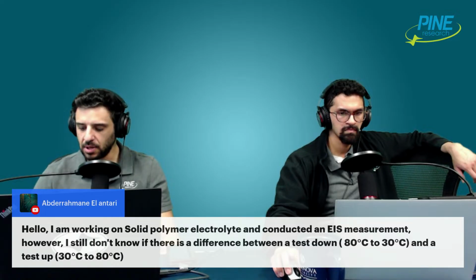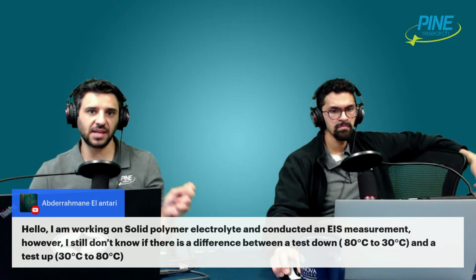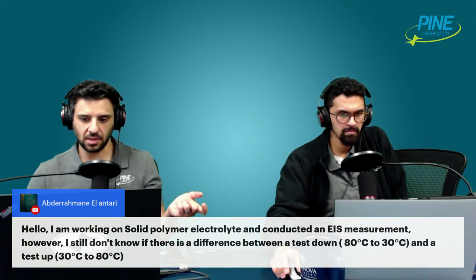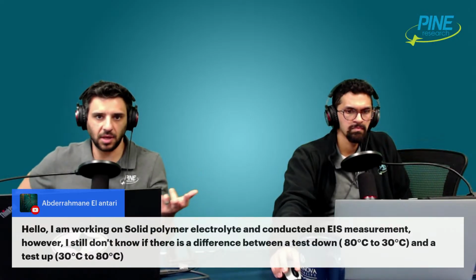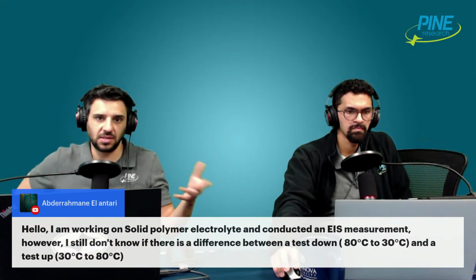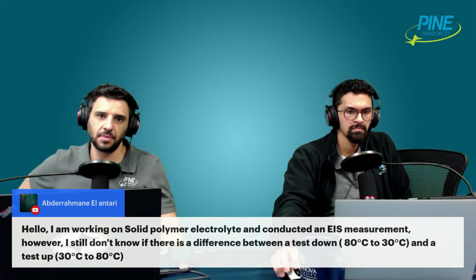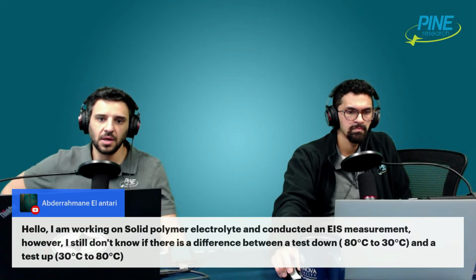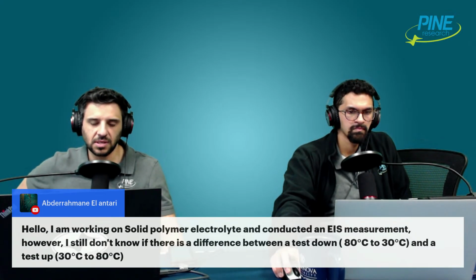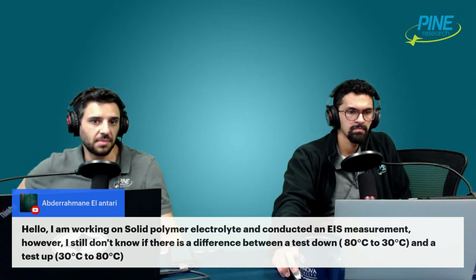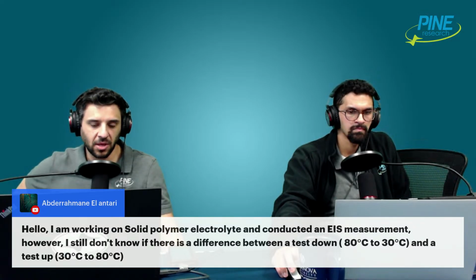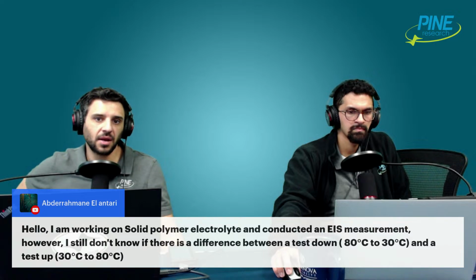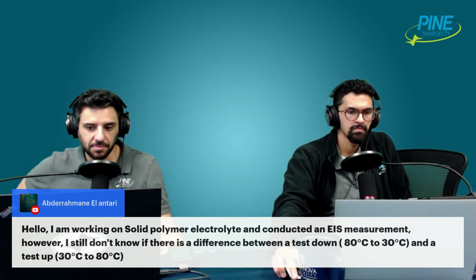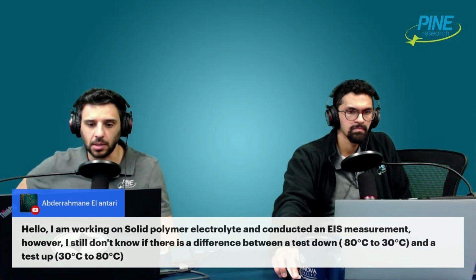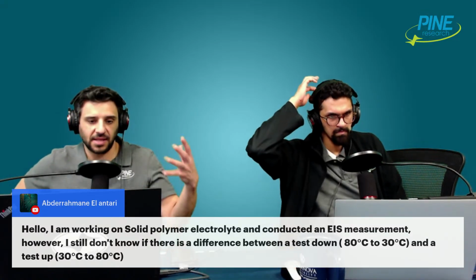But the point is, if that doesn't happen, then it's telling you something, obviously. One of them could be that the construction of your materials is poor, or you've made an error, and it's a time thing, like time spent testing is causing the material to decompose or delaminate or something of that nature. That's not good. Or, if you see a distinct difference between the temperature differences, then you've reached a limit where the temperature is irreversibly impacting your materials, right? But ideally, it should not depend on it if all the materials, not just the polymer, are thermally stable up to 80 degrees C. That's what you would hope to see.